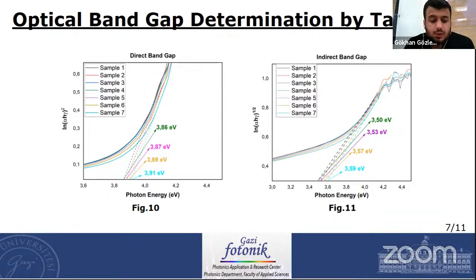Like the direct band gap calculation, the indirect band gap values have been calculated from alpha h-nu to the root versus h-nu plots and are shown in figure 11. Corresponding band gaps were obtained by extrapolating the straight portion of the graph to the x-axis at y-axis 0. The value of indirect optical band gap for sample 7 is 3.59 electron volts, sample 6 is 3.57 electron volts, sample 5 is 3.53 electron volts. Moreover, indirect optical band gap of films thicker than 15 nanometers is 3.50 electron volts.